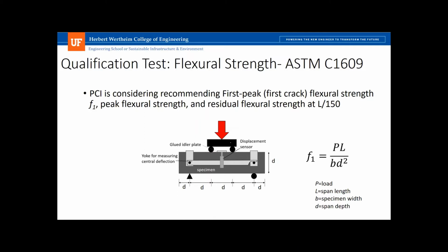It's a flexural test where we basically put a UHPC sample in flexure, a 4x4 inch cross section is typically used, and based on the load displacement curve, you'll see toughness parameters calculated and a first-peak flexural strength calculated as shown in the equation.